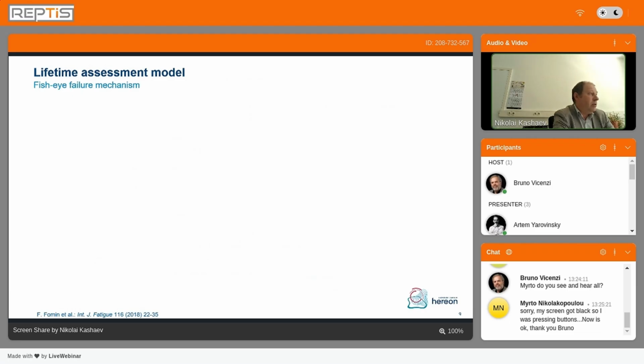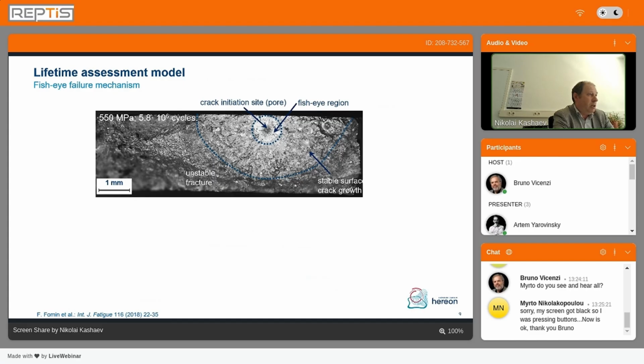If we analyze the fracture mechanisms for the condition without geometrical defects, we see that here the internal defects play a significant role. We have fish-eye crack initiation from internal porosity, and in this figure you can see clearly that we have, for example, several defects, and from two single pores we have at the same time fatigue cracks which were initiated and go to the surface, but the pore in the middle was the more critical one.